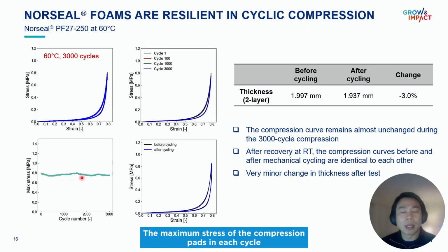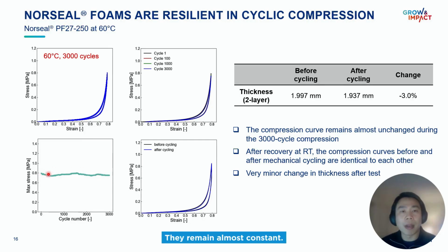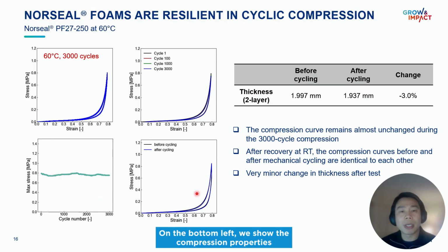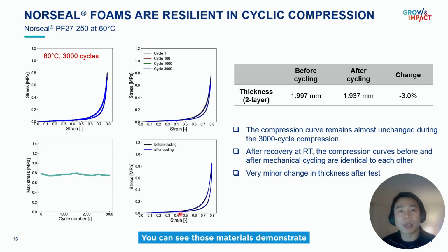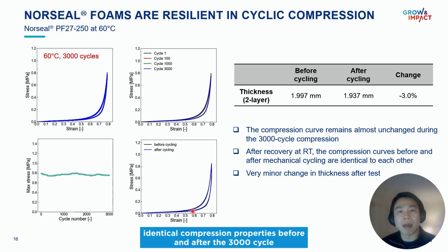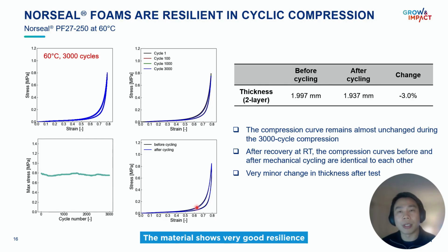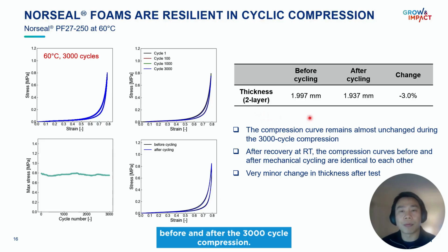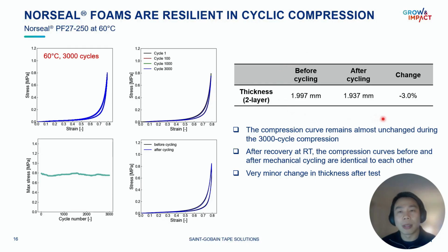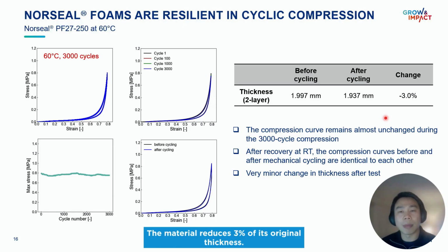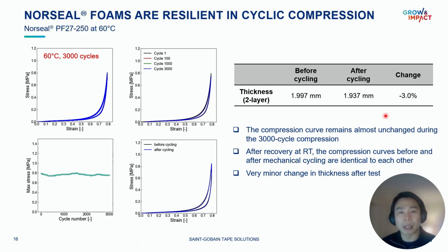The maximum stress of the compression pads in each cycle are plotted in this graph. They remain almost constant. On the bottom left, we show the compression properties of the compression pads before and after cycling. You can see those materials demonstrate identical compression properties before and after the 3000 cycle compression. The material shows very good resilience in terms of cyclic fatigue. We also checked the thickness change of the materials before and after the 3000 cycle compression. The change is very minor. The material reduces 3% of its original thickness.